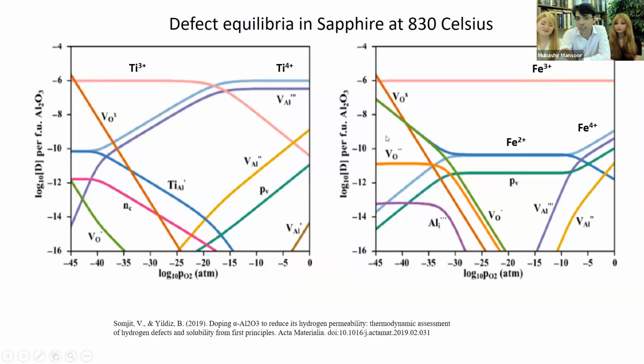They have shown what kind of defects from the iron and titanium occur as you heat them in different oxygen partial pressures at a constant temperature of 830 degrees Celsius. For example, they show that iron 3+ is the most dominant kind of iron valency that we would observe, regardless of the oxygen concentration. Now, if you reduce your oxygen partial pressure in the furnace, you would get more of these iron 2+.